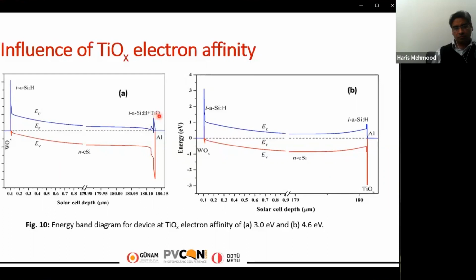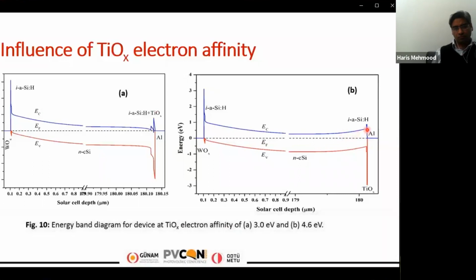But if we increase the titanium dioxide electron affinity to 4.6 electron volt as shown in figure B, then there will be some sort of band bending happening near the cathode interface as well. So this increase in the electron affinity of the titanium dioxide will try to trap the electrons at the cathode interface, thereby leading to the recombination, hence a decrease in the photovoltaic performance would be observed.